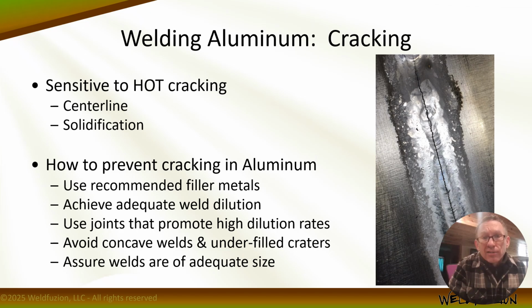Aluminum is also quite crack sensitive, but unlike hydrogen underbead cracking in steels, aluminum exhibits hot cracking or hot short cracking, which is at the centerline of the weld, and it occurs immediately upon or shortly after weld solidification. Some aluminum alloys can be welded without filler metal, but many require specific filler metal combinations to prevent this hot cracking. For example, 1100 aluminum is relatively pure and can be fusion welded or autogenously welded without filler metal. However, 6061 aluminum has both silicon and magnesium as primary alloying elements that require a filler metal with one or the other, but not both.